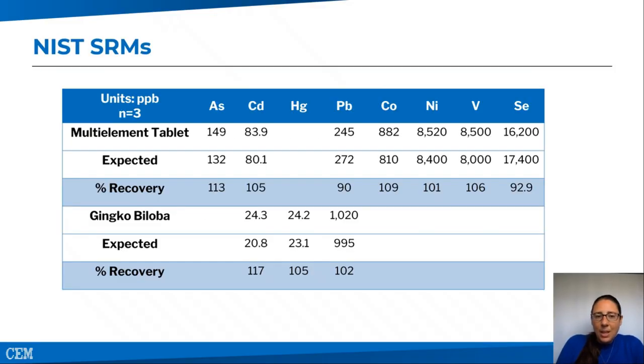So let's look at the data. As noted, we're going to first start with our SRMs. We have the multi-element tablet and the ginkgo biloba. There's a lot of numbers on the screen here, so let's take a moment to break them up. What we've got is what was detected. Again, this is an average of N equals 3, and all the units you see here are in ppb, parts per billion. So what we actually detected in the sample, the actual concentration of what was expected, and then the percent recovery that you achieved with those. That's the list going down.